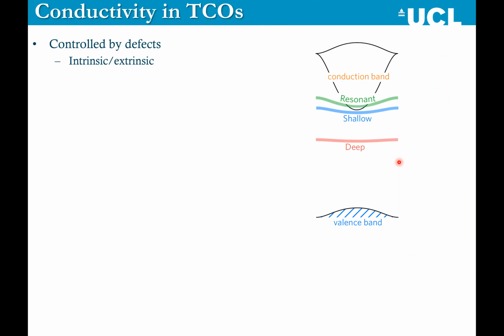So of course, conductivity in these types of solids is controlled by defects, be they intrinsic or extrinsic. And we normally characterize these types of defects in these systems into 3 different groupings. So you can have a deep defect. That's one that is very, very far away from the band edge. So it has to be excited to get an electron from the deep defect state to the conduction band where it could be mobile. A shallow defect is one that is quite close to the conduction band, so that it only needs a small amount of energy to be excited.